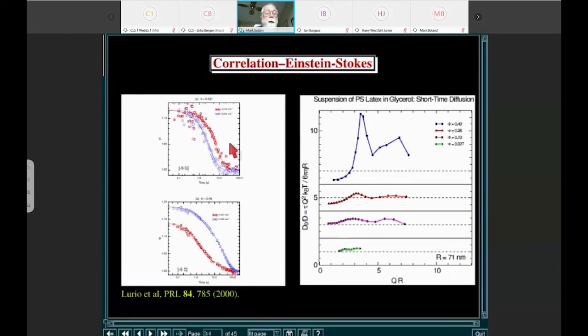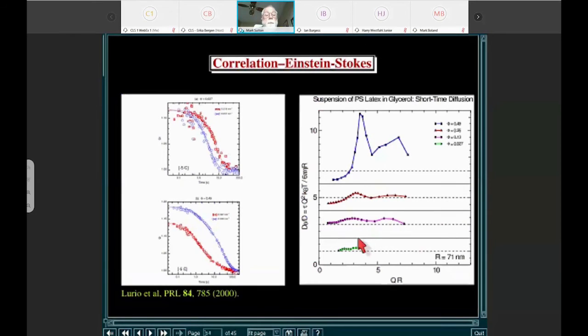We can then look at what the time constant or the effective diffusion constant is as a function of Q, and for independent scattering, like at small volume fractions, we basically just get Einstein and Stokes diffusion theory, and we can see the diffusion constant is independent of wave vector. But as we go to higher and higher concentrations, the diffusion constant becomes wave vector dependent.